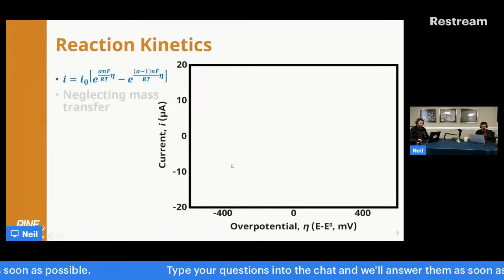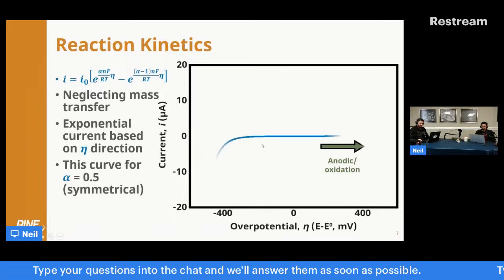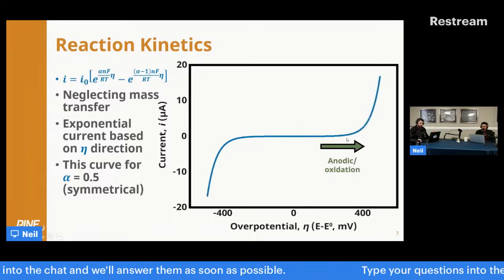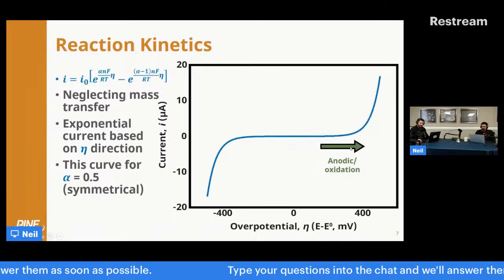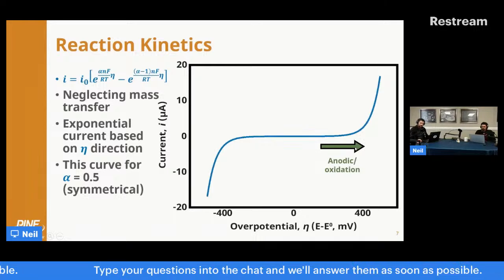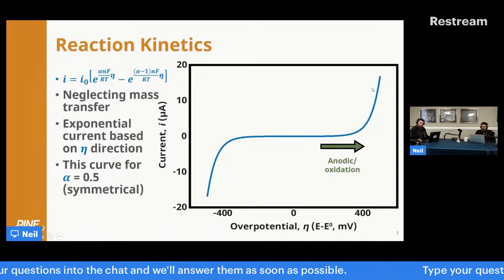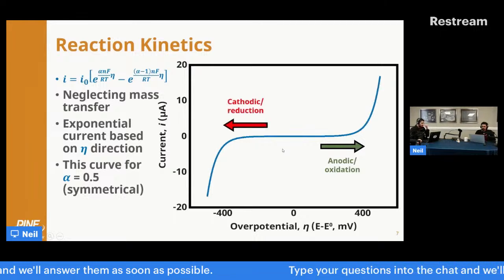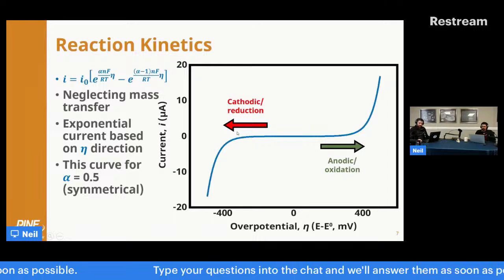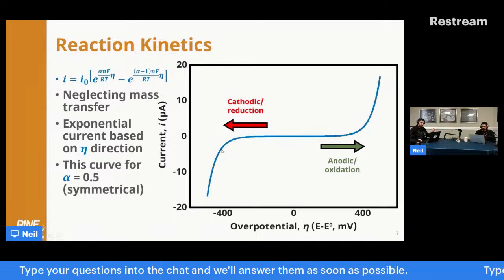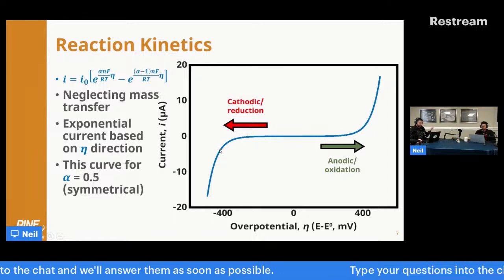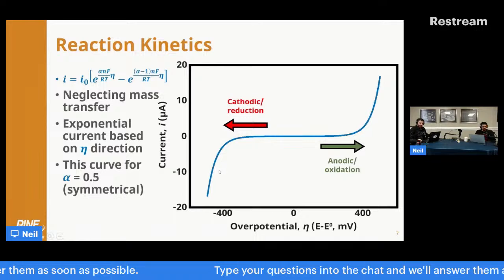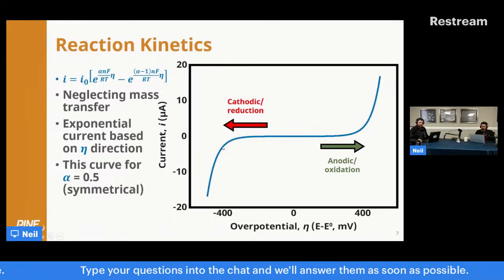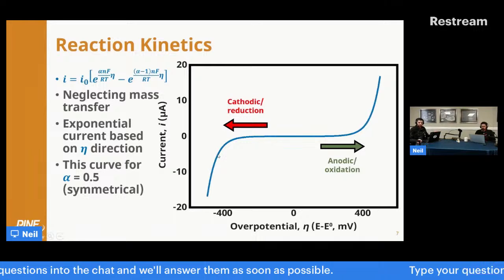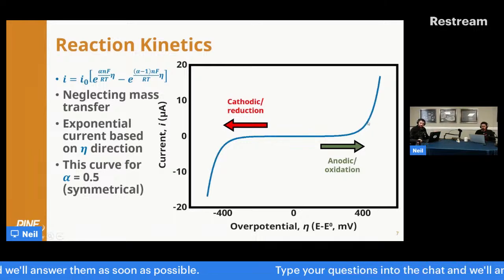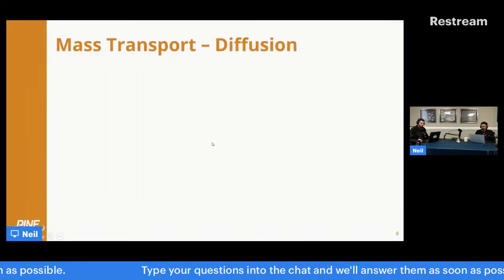When we plot current versus overpotential, we get an exponential looking plot, and it depends on the direction. As I go positively in overpotential with the IUPAC convention, we have an exponential increase in current. As I go negatively, I have a cathodic reduction, an exponential increase in the negative direction, either way you want to say it, in my current. That is the beginning of a peak that occurs in a cyclic voltammogram. It usually looks like this. The current starts to increase or decrease depending on which direction you're moving.